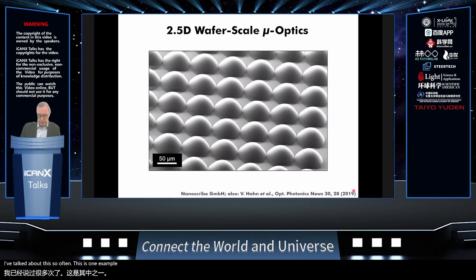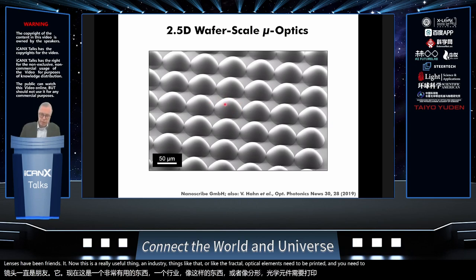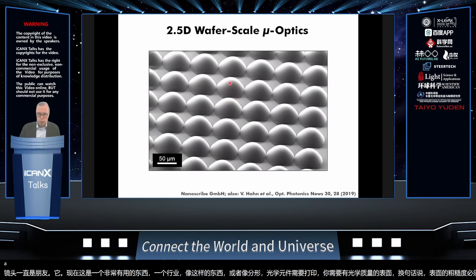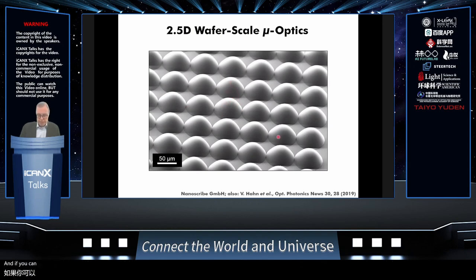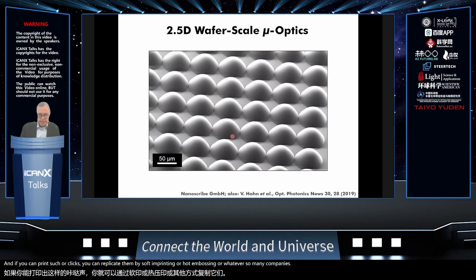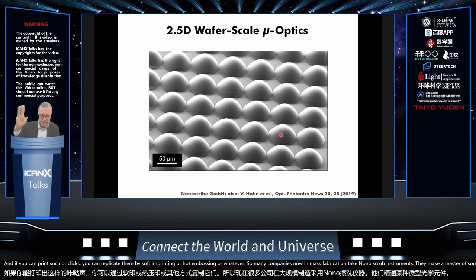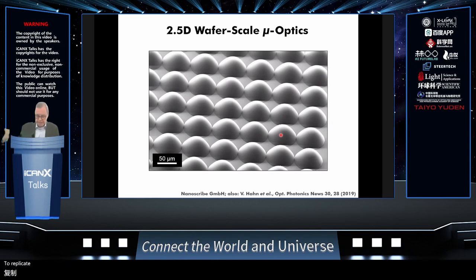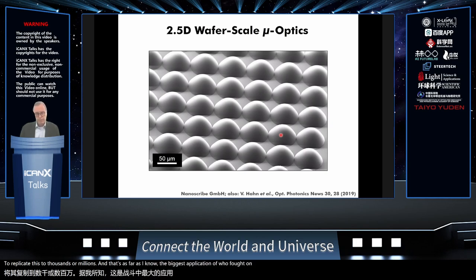This is one example taken from this reference, where lenses have been printed. Now, this is a really useful thing in industry. Things like that, or diffractive optical elements, need to be printed, and you need to have optical quality surfaces. In other words, the roughness of the surface must be on the scale of just a few nanometers root mean squared. And if you can print such optics, you can replicate them by soft imprinting or hot embossing and whatever. So many companies now in mass fabrication take Nanoscribe instruments, make a master of some micro optical component, and then use some sort of stamping technique to replicate this to thousands or millions. And that's, as far as I know, the biggest application of two-photon absorption-based printing these days.